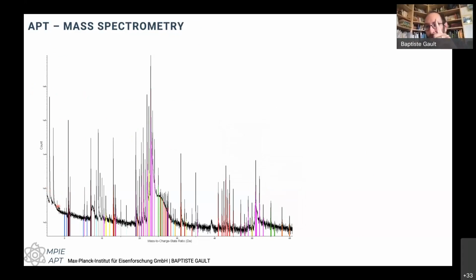So we detect hydrogen 1, just 1 hydrogen at 2 hydrogen, so H2 1+. And depending on the electric field conditions, we can actually form H3 1+. This is a metastable species, but it's well known in the high field community. It happens quite often. So the problem is that there's always some hydrogen in the chamber.